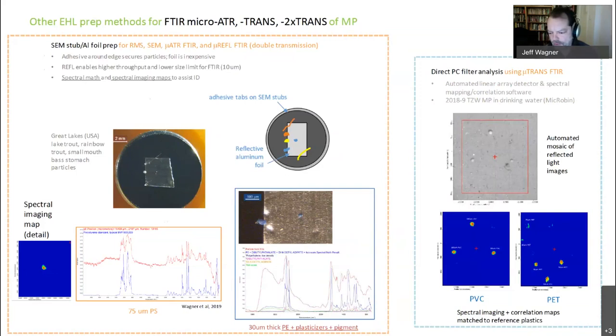On the lower right, you see two different spectral imaging maps, specifically correlation maps that we're generating using our reference microplastics. So they both correspond to the same red box in the mosaic reflected light image above it. It's just that the lower left one highlights only the PVC particles that were present in that image, and the lower right hand correlation map only shows the PET particles.